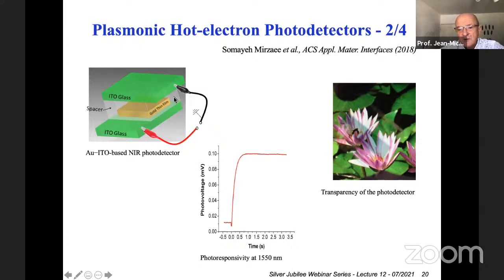looks brownish when you look at it. It's called, technically in the literature, black gold, but we have a very thin layer, so the absorption is very tiny. And if you want to see the absorption, actually the glass plate is 2 centimeters by 2.5 centimeters. There is a stripe of gold, and the gold is just creating that shadow that you see on top of an image of lotus flowers for the decoration of the figure.